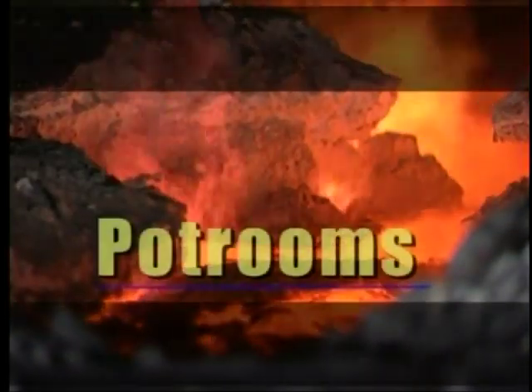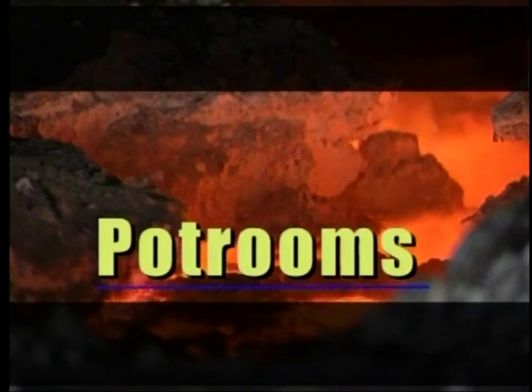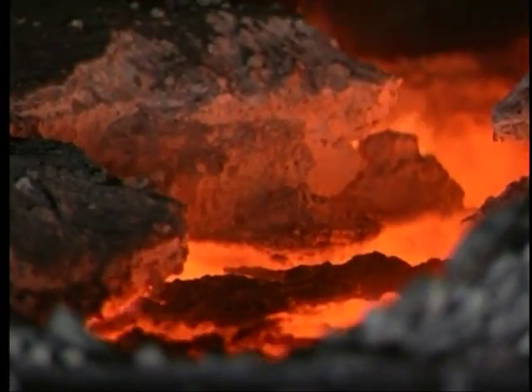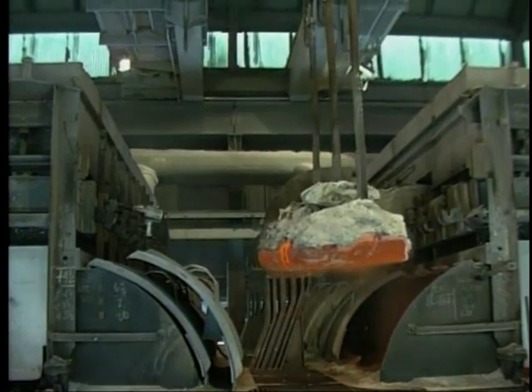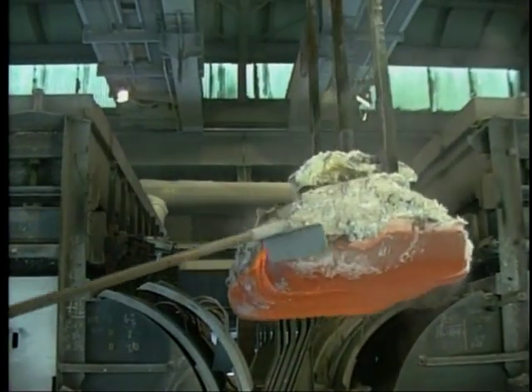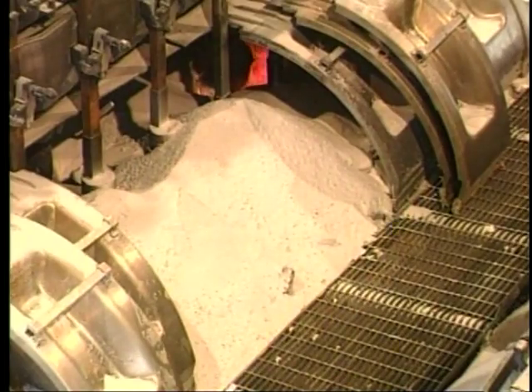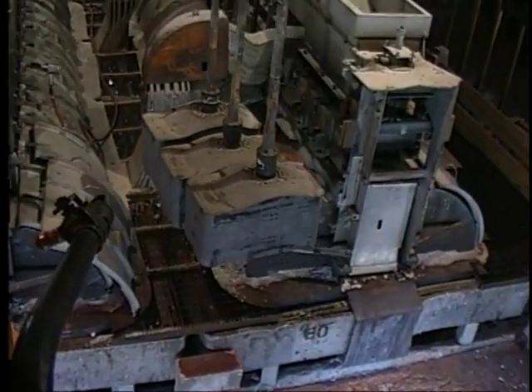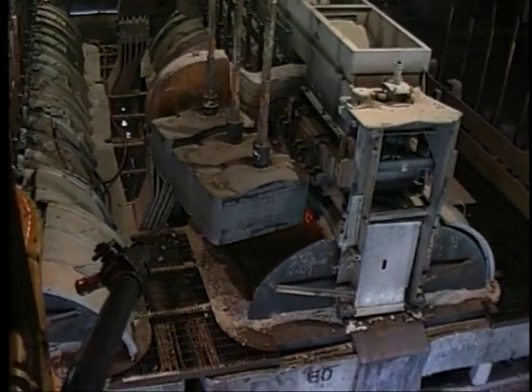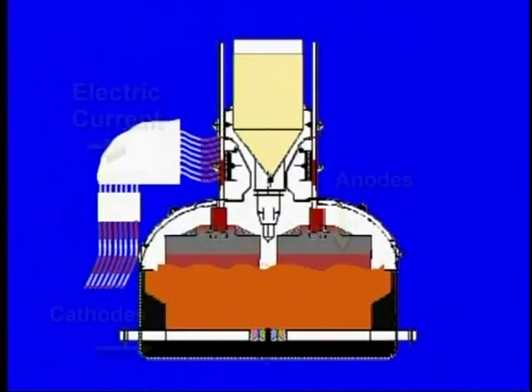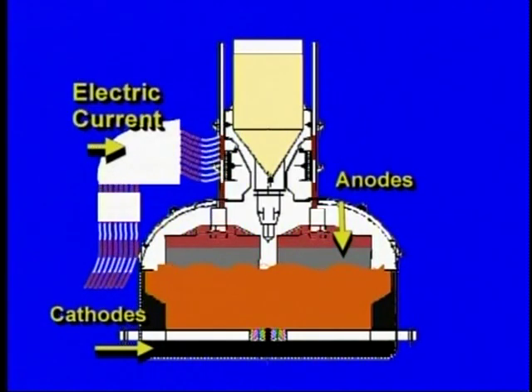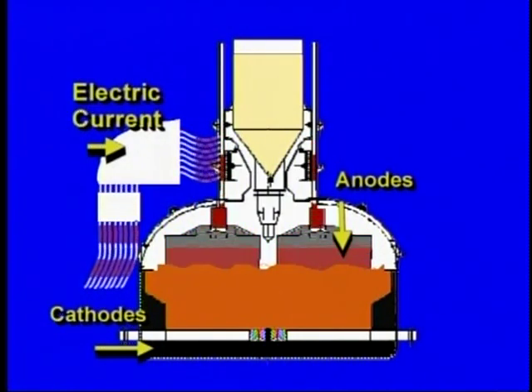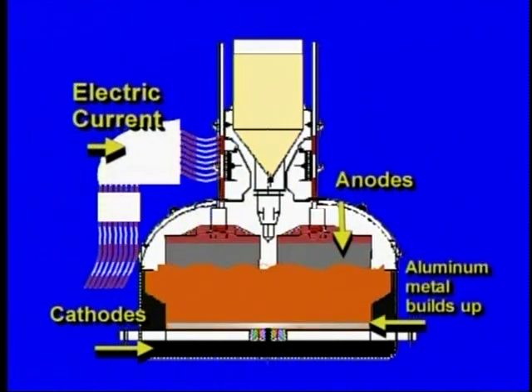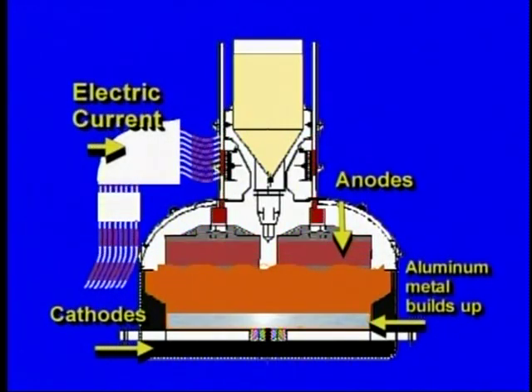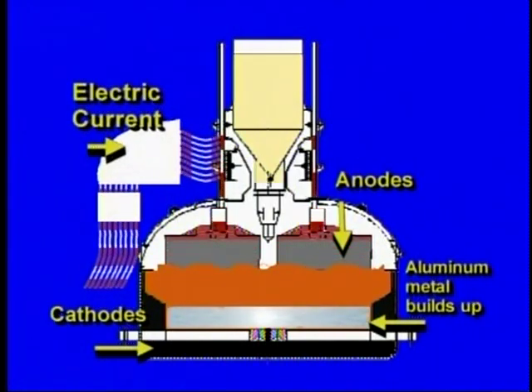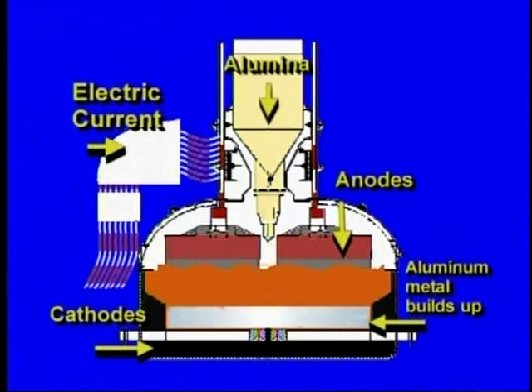To get aluminum metal, alumina powder brought by rail to Rockdale must be smelted or reduced, using the electrolytic Hall process to separate the aluminum and the oxygen. This is done by dissolving powdered alumina in a cryolite bath, inside large, carbon-lined electrolytic reduction cells called pots. When a powerful direct electric current is passed through the bath from the carbon anodes to a carbon cathode, the alumina is reduced to aluminum metal. Heat generated by the electricity keeps the bath liquid at about 1800 degrees Fahrenheit, so more alumina can be added to make the process continuous.